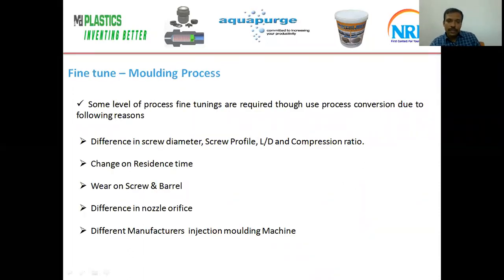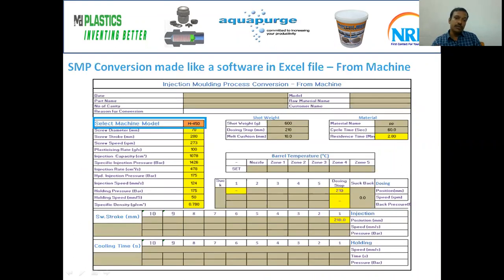See, after conversion, these process parameters may still require some amount of process fine tuning because of differences in screw diameter, screw profile, L/D ratio and compression ratio, changes in residence time due to screw diameter, wear and tear of the screw and barrel, differences in nozzle orifice, and different manufacturers' injection molding machines.